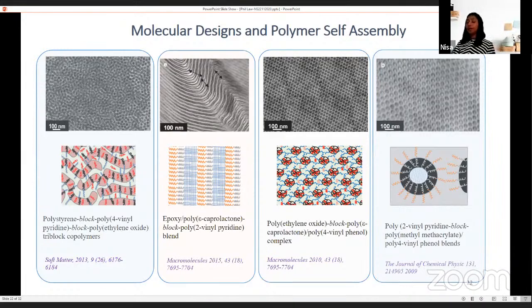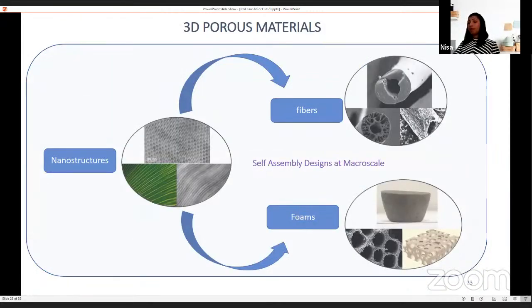In summary, we have created various nanostructures both in solution and solid state. We can control the morphologies, or switch the morphologies, by changing their molecular weight or chain length, or even the composition of each block in the block polymer. We have also derived a mechanism for these materials to understand the structure formation. In the current study, we are adopting designs from nature to create various porous materials by using this self-assembly approach. These nanostructures were translated into macro scale materials while preserving the order and self-assembly at nanoscale.